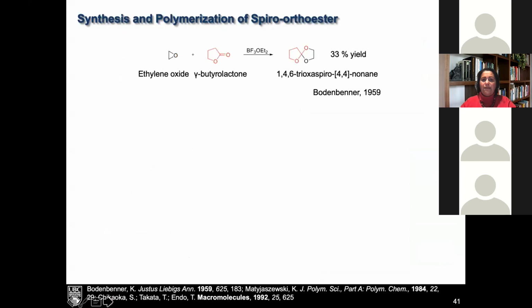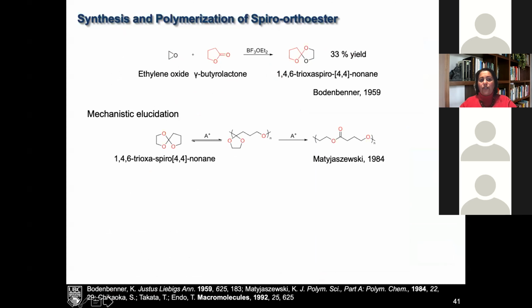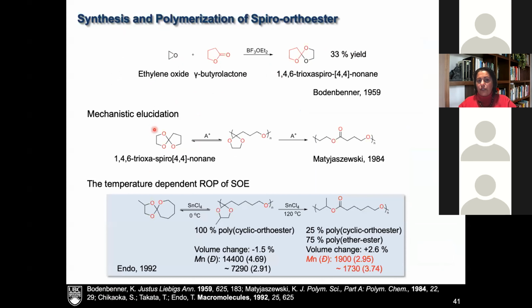And what this meant to us is that if you think about in the literature the formation of spiro orthoesters, this is a simple reaction where you take an epoxide and a lactone and you get a spiro orthoester. The yields are about 30%. In the literature, people like Matyjaszewski have shown that you can polymerize them through a cationic mechanism. And Endo and co-workers in the early 1990s really explored the polymerization of these materials.